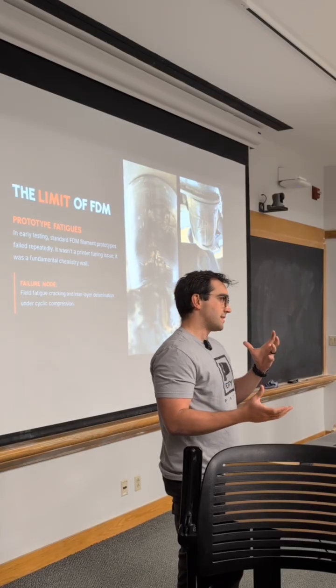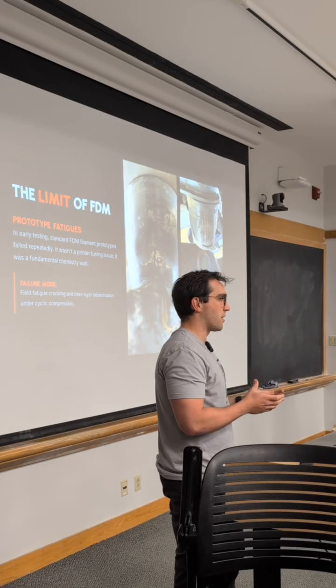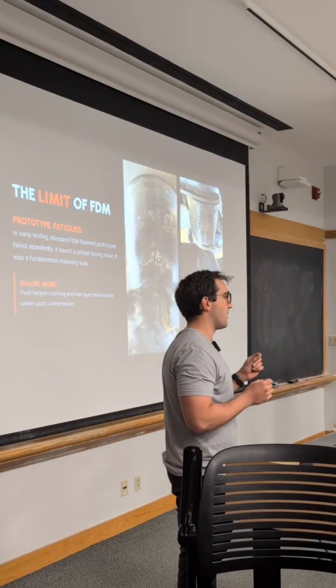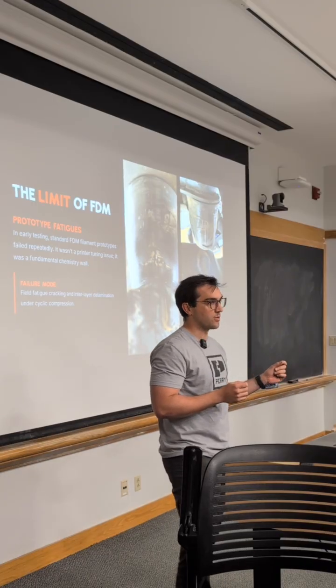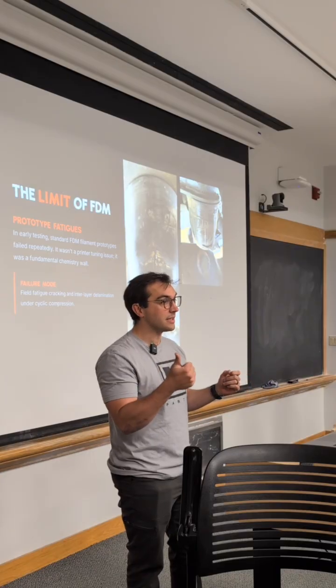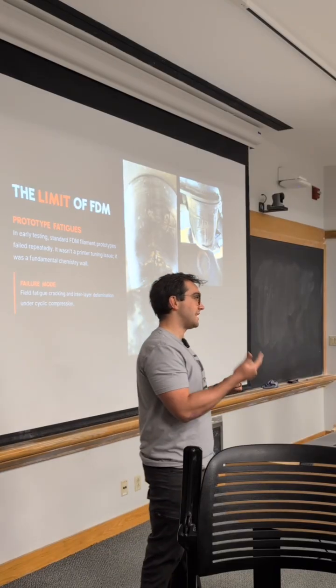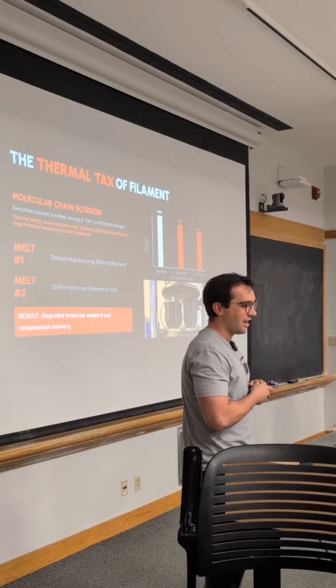We found this to happen in high stress locations on the parts, but it really correlated much more heavily with time in field, which means that either something's happening chemically with the material or there's a fatigue failure happening with the material.